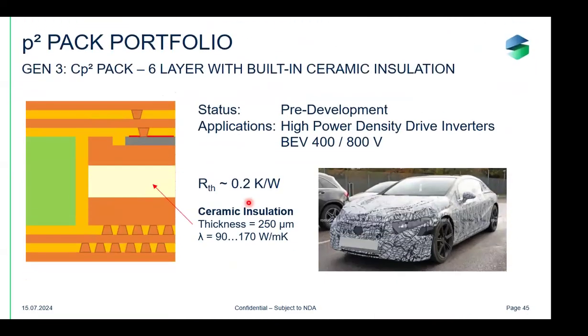And that was the reason why we went to generation 3, because with generation 3, if you use this ceramic substrate, you have a much higher thermal conductivity of the ceramic substrates in comparison to the organic material in generation 2. So depending on the kind of ceramic that you use, silicon nitride or aluminum nitride, the conductivity is 90 to 170 watts per meter Kelvin.